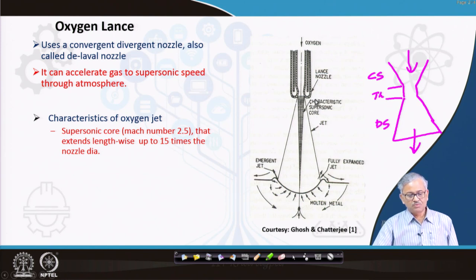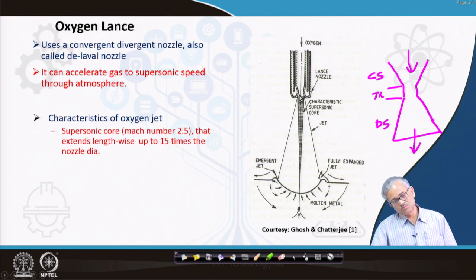Why? Because when the oxygen jet is moving through the atmosphere, it entrains a lot of air into it. And that's why this portion, this is also a jet, this is a complete jet, you can find. But a portion of this jet becomes subsonic, because the velocity is reduced since you are entraining a lot of air into it. So, you are increasing the mass, and as a result velocity is decreasing. So, this is the subsonic portion, and this region is called the supersonic portion. And what is the length of this supersonic core? It has been found that it is around 15 times the nozzle exit diameter. So, it extends up to that, right? So, this is one of the important characteristics.